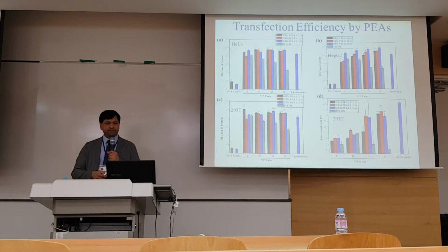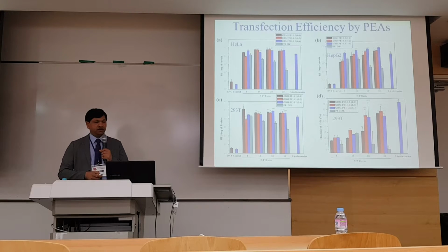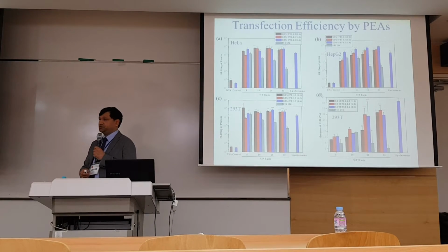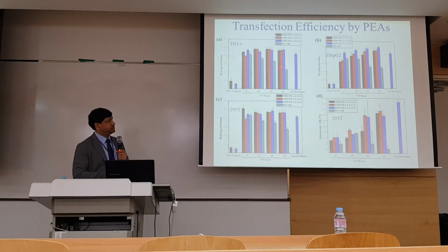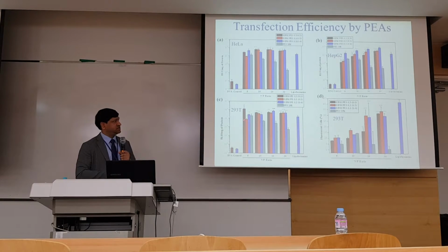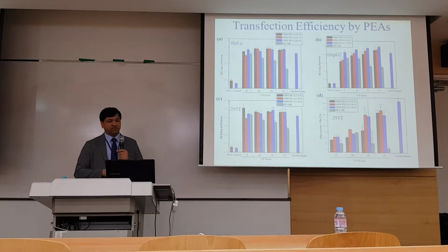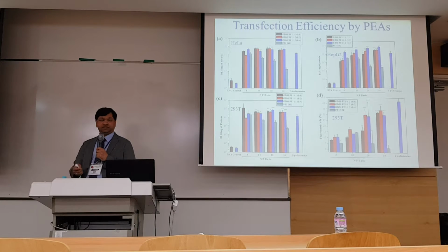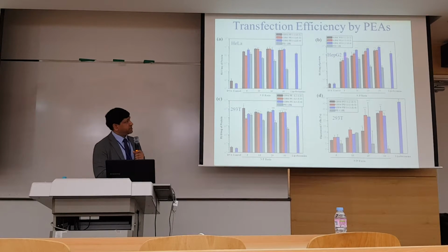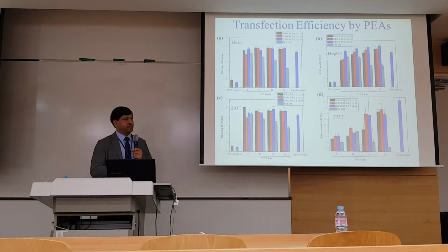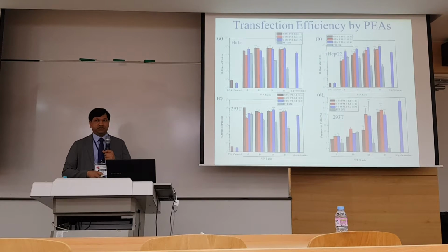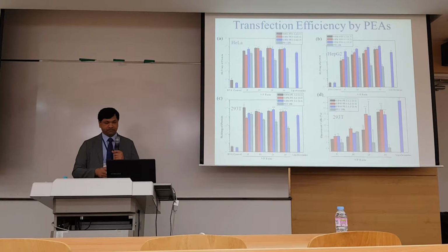That leads to toxicity. By checking the transfection efficiency by luciferase assay using the pGL3 as a reporter gene, you can see here in all these three different cell lines, 293, HepG2 or HeLa, the polymers had high transfection efficiency compared with PEI 25K, and also compared with lipofectamine as another control. So that indicates the advantage of the ester linkage in the backbone of the polymer.